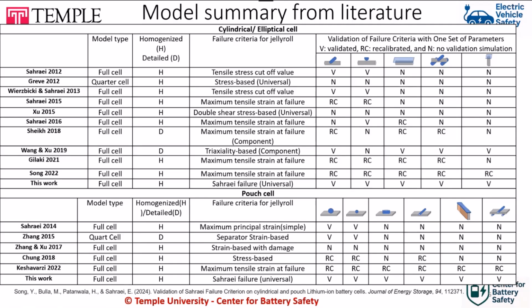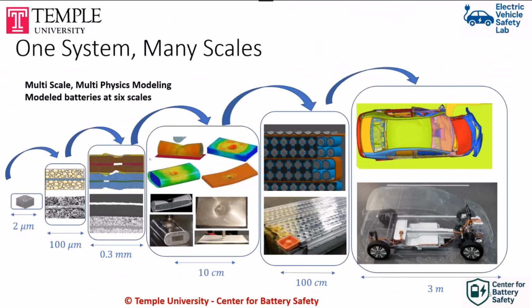And it includes hemispherical loading, plane strain loading with rod, in-plane loading, 3-point bending, and we can predict when short circuit happens. So the way our understanding has developed over the years from 2010 to now